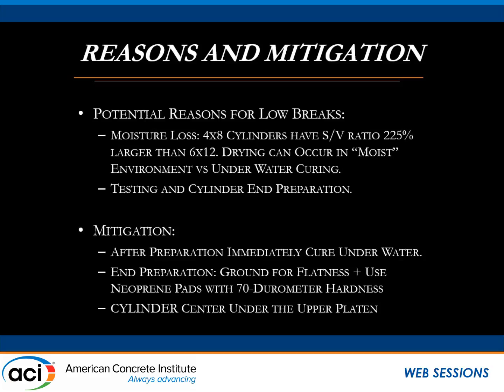And then the next thing, they started looking at the preparation of the cylinder ends. Even though the ASTM standard says you shall not use neoprene pads above 12,000, they looked into that, besides grinding and saw cutting the top to 0.002 inch flatness. They did some qualitative studies on the neoprene pad and decided to use the 70 versus the 90 to make a difference. Then by saw cutting and using a neoprene pad, the concrete strengths went back to what the history of that mix was to begin with.